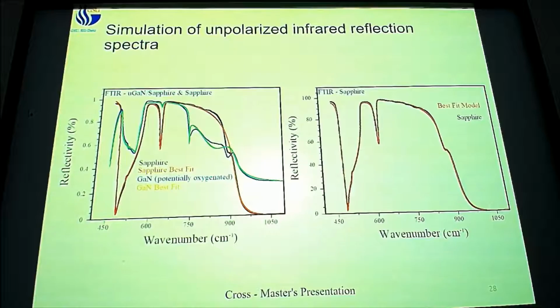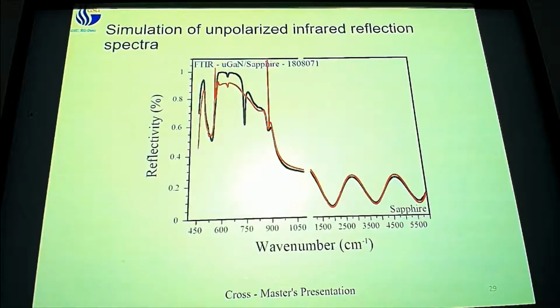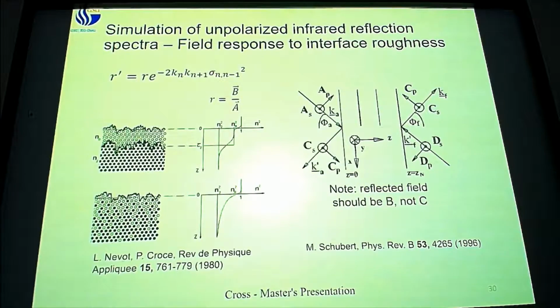So I took the polarization into account and I started working on it, and I got to this point here. I compensated for that and I compensated for that. Now I need to extend it to more than just one layer. Basically I just modeled the reflectance at a single surface of sapphire. What about gallium nitride on top of sapphire? When I did that, it didn't work, so this is what I'm continuing to work on. It turns out there were some problems with the model I was working with. So I'm going to extend that model a little bit and try to get this to work. That's my continuation. I'm also going to work on getting the roughness modeled.